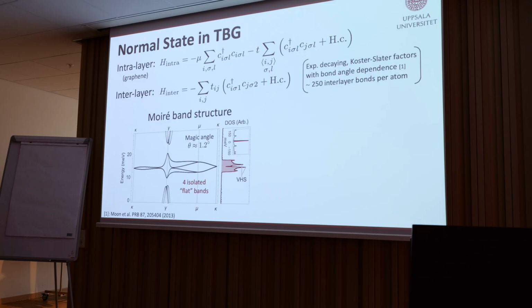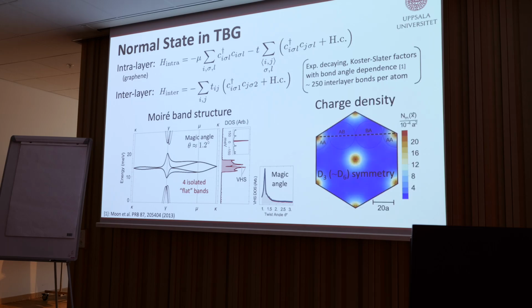And the accurate band structure in our case looks like this. Here we zoomed in on the small energy regime of the Moiré band structure. You have four spin degenerate, isolated flat bands, and we get small band gaps to the other states. Here you see the density of states, and it's high throughout, but there are also clear van Hove singularities. We can also see that there is clearly a magic angle dependence. Here we plot the peak height as a function of angle, and it clearly peaks at a specific angle. That's where you get the flat spectrum. And if you plot the charge density in real space, it looks like this. This is the Moiré cell, and we see that there are a lot of electrons sitting here in the AA region, and we don't have many electrons sitting in the AB and BA regions.